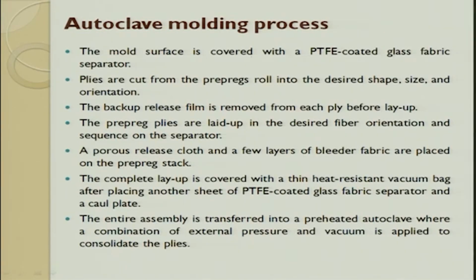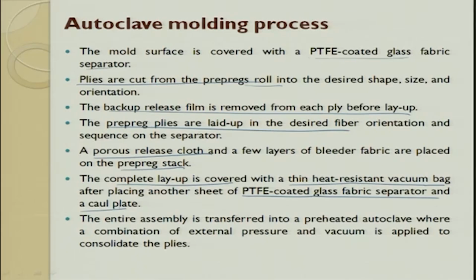The mold surface is covered by a coating of a separator, so that the part can be removed. The plies are cut from the prepreg rolls. The releasing film, which is on the top and bottom, is removed for each ply, and it is laid. The prepreg plies are laid in the desired orientation, which we have already discussed. A few layers of porous release cloth are placed on top of the prepreg stack. Then the complete layup is covered with a thin heat resistant vacuum bag, placed on a sheet of PTFE coating, which separates it from the caul plate. The entire assembly is transferred into a preheated autoclave to get the consolidation.